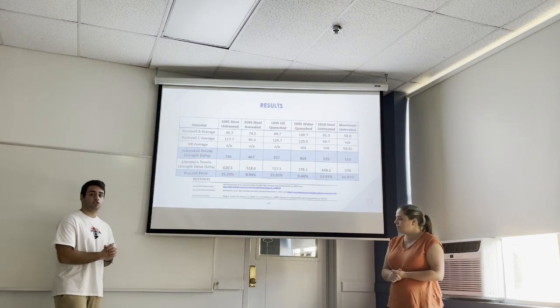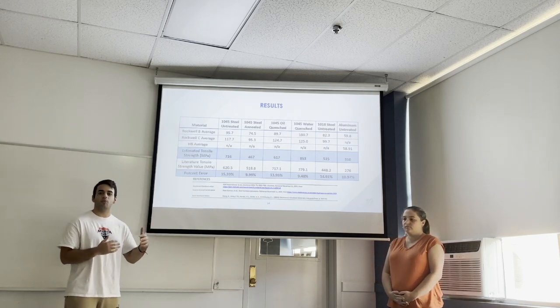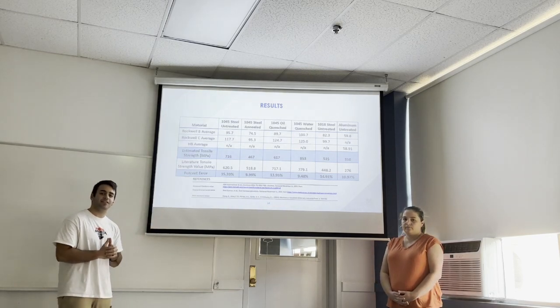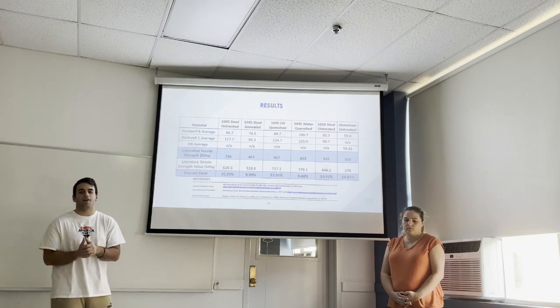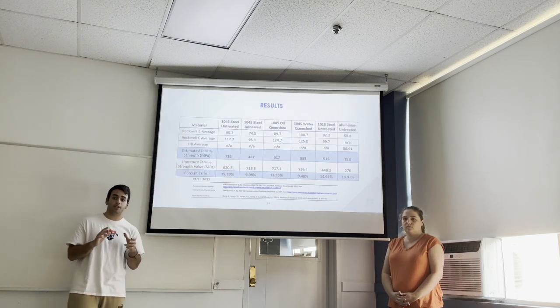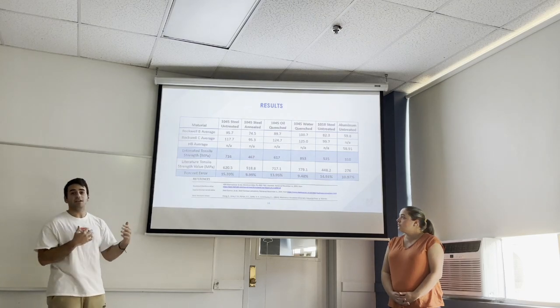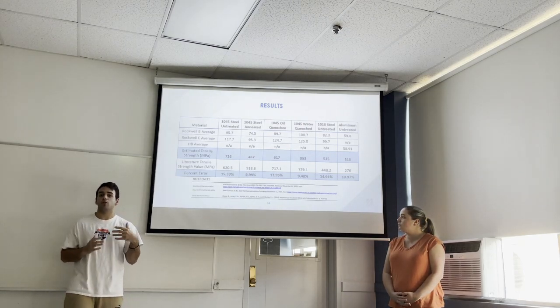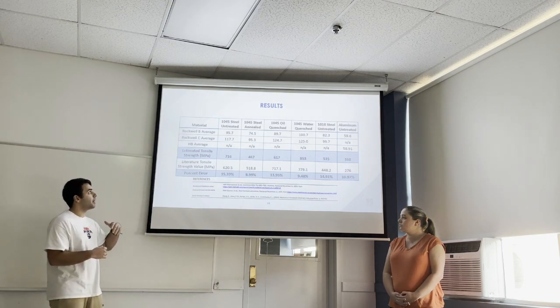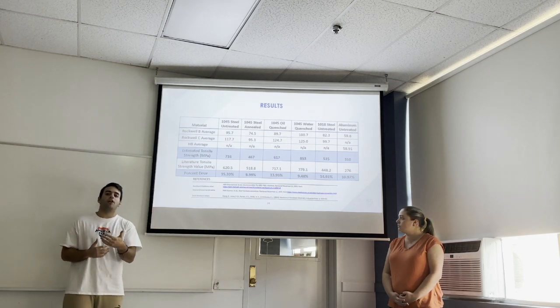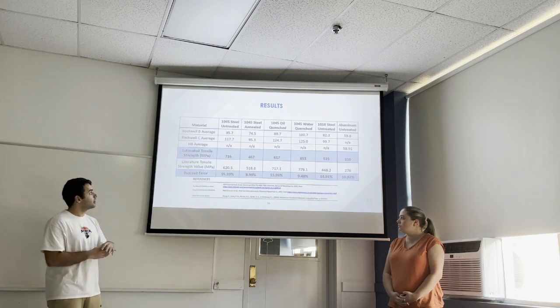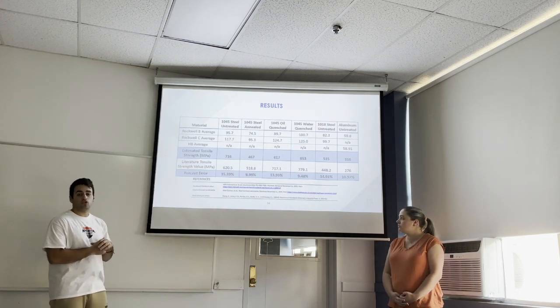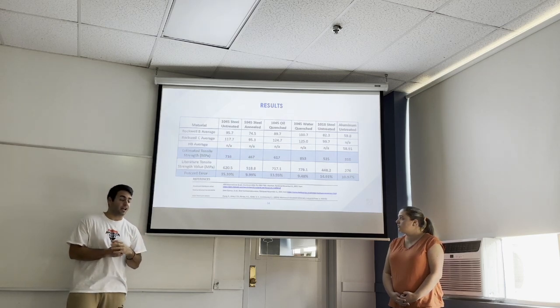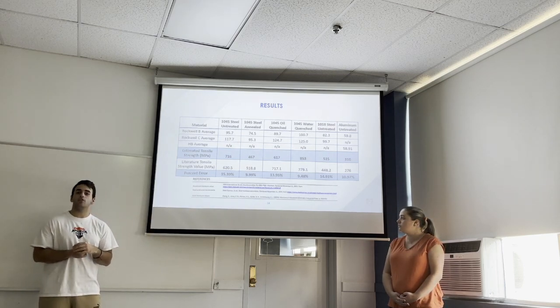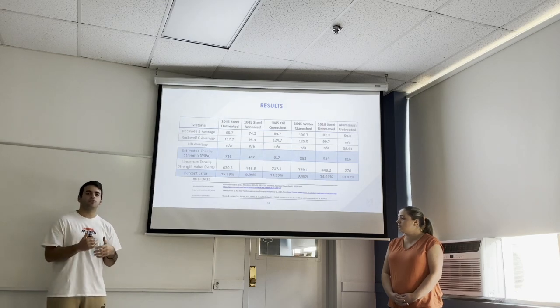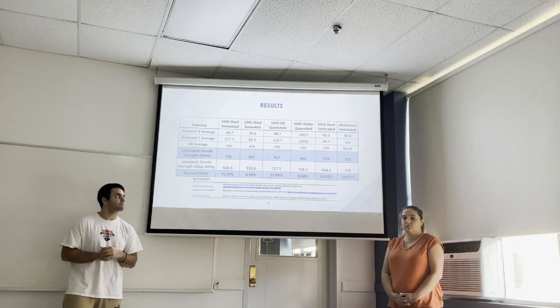All right, so in terms of overall results, for the 3 different materials, we found that aluminum was the softest of the 3, followed by 1018 steel, and then the hardest material was 1045 steel. When we look at the difference between the heat treatments of 1045 steel, we found that the annealed steel was the weakest, actually being weaker than 1018 steel, followed by the untreated, then the oil quenched, then the water quenched being the hardest. When we look at all the estimated tensile strengths for each heat-treated material and compare that to the literature found values, we found percent errors ranging from 9% to 15%.